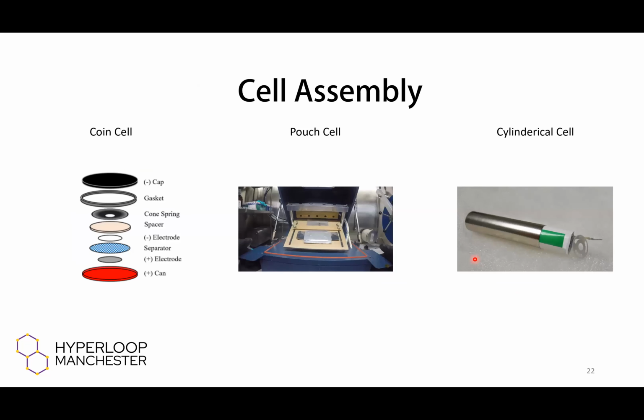Then it goes on to cell assembly. This hasn't got so much detail here, but the main one in the middle is actually this pouch cell assembly. This is done by hand. This isn't how they do it in industrial systems, but in principle it's the same. You have a vacuum chamber with a heated element at the top, and the lid would come down, it would pull a vacuum inside of the cell, and then these heated jaws would come down together and seal the edge of the cell. And because you sealed it under vacuum, when you return the cell to ambient pressure, you've then got atmospheric pressure pushing down on the cell and sort of forcing it together and compacting it. That's for a pouch cell.